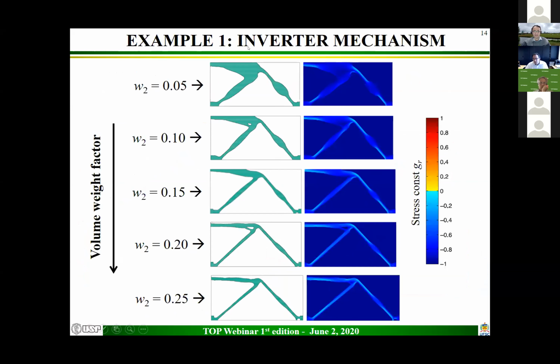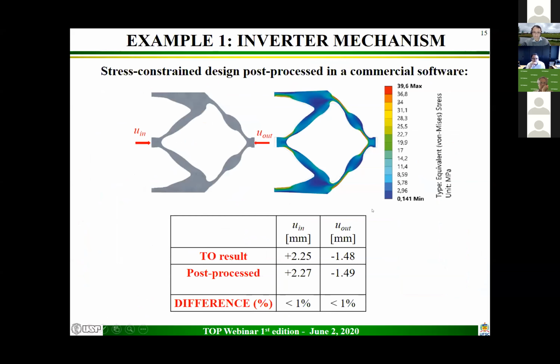We solve the same problem by changing the volume weight factor. That's the factor that multiplies the volume fraction term in the objective function. As expected, as we increase the value of the weight factor, we decrease the volume of the structure domain. In all cases, we obtain a hinge-free design and the stress constraints are satisfied. We also validate our stress constraint design problem by post-processing in a commercial software. So you can see here that the post-processed result still satisfies the stress constraint. And when comparing the displacements of the topology optimization result and the post-processed result, the difference is less than 1%.